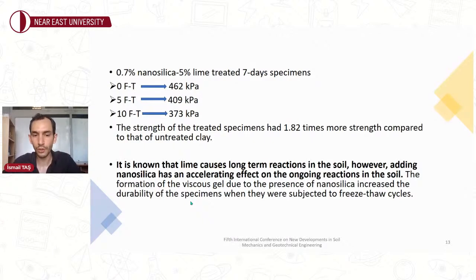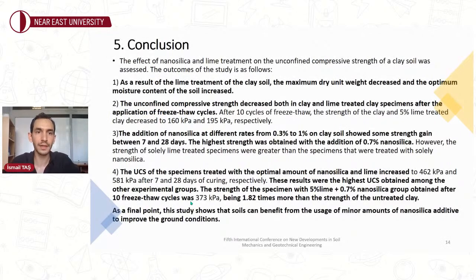It's known that lime causes long-term reactions in the soil. However, adding nanosilica has an accelerating effect on the ongoing reactions in the soil. The formation of the viscous gel due to the presence of nanosilica increased the durability of the specimens when they were subjected to freeze-thaw cycles. So the effect of nanosilica and lime treatment on the unconfined compressive strength of clay soil was assessed. The outcomes of the study are as follows.